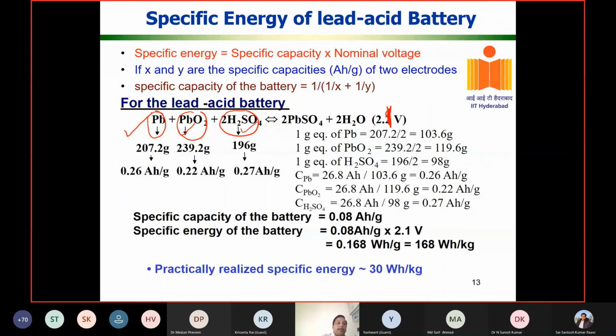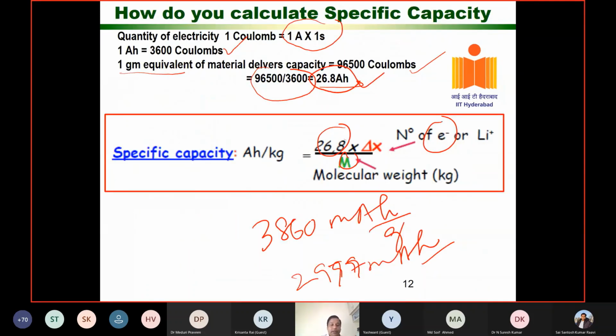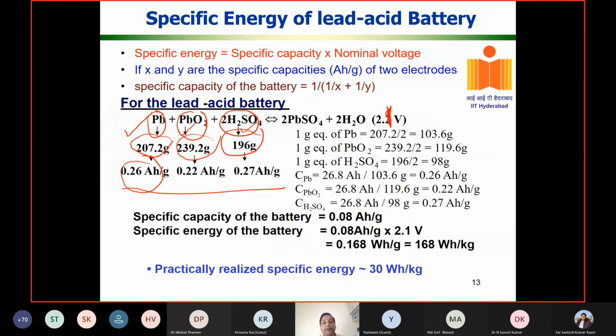If you calculate, 1 gram equivalent of lead is 207 gram per mole. 1 gram equivalent of lead dioxide is 239.2 gram per mole. 1 gram equivalent of sulfuric acid, so this is a 2 gram equivalent, so 1 gram equivalent will be around 98 gram per mole. So you can easily calculate the specific capacity. Just now I was talking, lithium is 3,860, and here you have 260 milliampere hour per gram. 1 gram of lead can give 260. In real, maybe we have developed better active materials. It can give you around 100 milliampere hour per gram or 120 milliampere hour per gram.